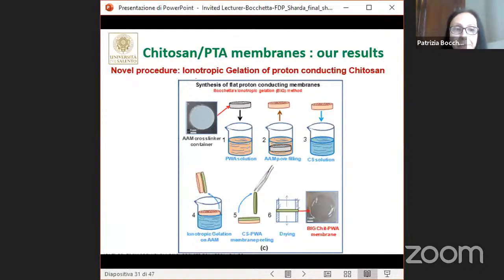During this step, chitosan, a cationic polyelectrolyte, and the phosphotungstate anions give place to ionotropic gelation, forming a proton-conducting, self-standing membrane at the alumina sides exposed to the solution. Step 5. This film can be peeled off the alumina support, and finally, the obtained self-standing samples were located in between two cylinders in order to avoid the wrinkling phenomenon during the drying process.